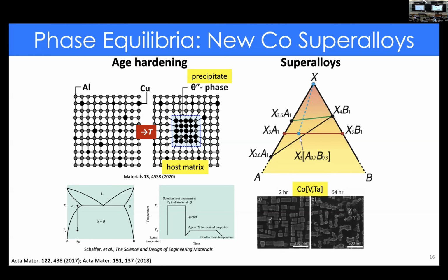What we want to understand from a computational perspective, and we map this to our phase diagram here, is that let's imagine we have a set of compositions here, the red line, that we know could be this precipitate composition. That's the range of compositions that this precipitate could be. We want to understand, is it possible that we can form this blue line here, mapping the host matrix, basically pure aluminum, to the set of compositions that the precipitate could take form in? You can imagine that if I have a facet line that looks like the green one here, as I scan all the different ternary combinations, if this facet line exists, this blue line will not exist.